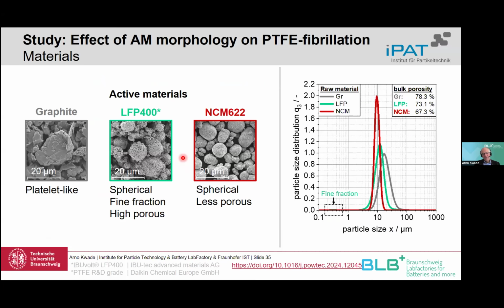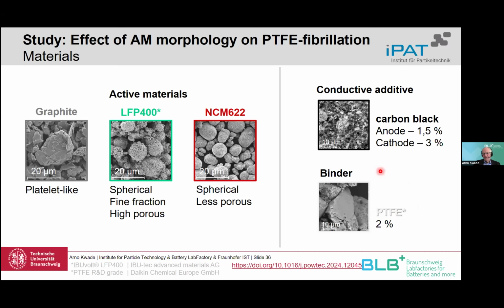And this has then a crucial effect on the coating, but also on the later electrode performance. Here today, I want to show you a comparison of different materials, so how we can process graphite, LFP, and NCM. We also published that already in Powder Technology, how these particle structures, sizes, also densities affect at the end the fibrillation and the final electrode properties. And you see that here the NCM is in the size of almost 10 micron. LFP is a poly-dispersed LFP, so it's even a little bit larger or coarser. And then we have the graphite, in this case also even a little bit coarser again. And we use some carbon black for an anode, it's 1.5%. For the cathode, it's 3%. And in any cases, we had 2% of PTFE.